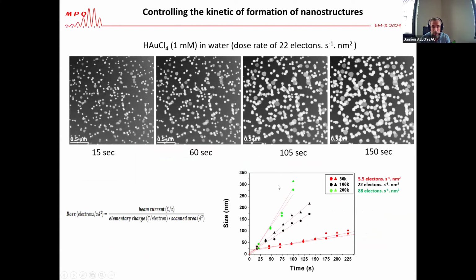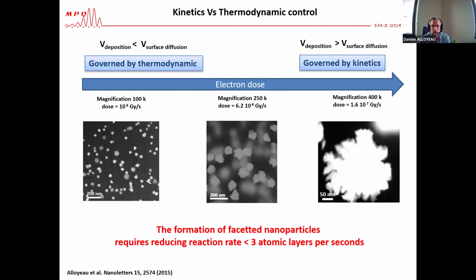And now you can observe what is the effect of increasing the growth speed. You see that when you are at low magnification, meaning low dose rate, meaning low growth speed, you form faceted nanoparticles. When you increase the magnification, you increase the growth rate, and you start having those branched morphologies. And if you go to very high magnification, you start having those very rough surfaces. So you can interpret this result this way: the shape of the nanocrystals depends on the competition between the deposition speed and the surface diffusion speed.